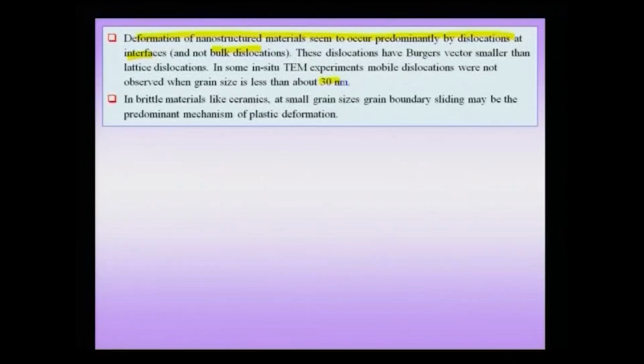Additionally, a few more points to be noted are that deformation in nanostructured materials seems to occur predominantly by dislocations at interfaces and not bulk dislocations. And of course, we are talking about very small grain sizes of the order of about 30 nanometers. We are not talking about really large grain sizes of 100 nanometers and more, where you can have bulk dislocations. You can continue to have pileups, Orowan bowing and Frank-Read mechanisms, but when you go to really small grain sizes, then dislocations at interfaces seem to play a very, very important role.